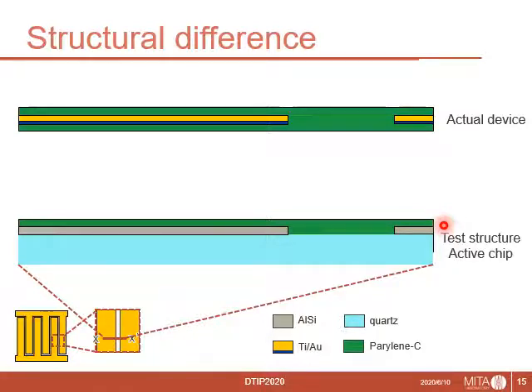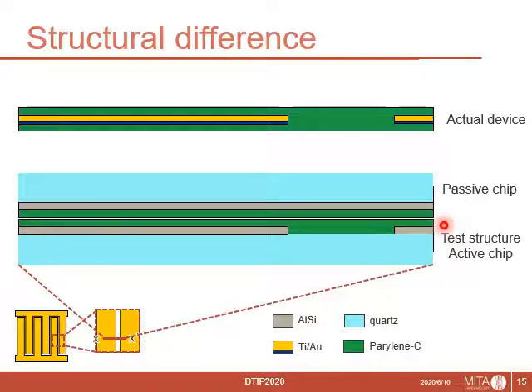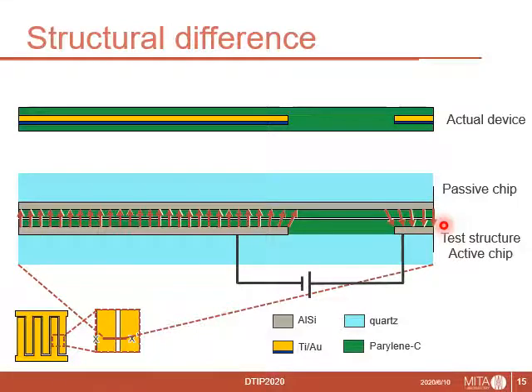The structural difference of the bottom side can be ignored when the active chip faces the passive chip closely, because electric field only exists between the active chip and the passive chip. Secondly, electrode material on the test chip was aluminum silicon, not gold, but the kind of metal doesn't affect the strength of adhesion.